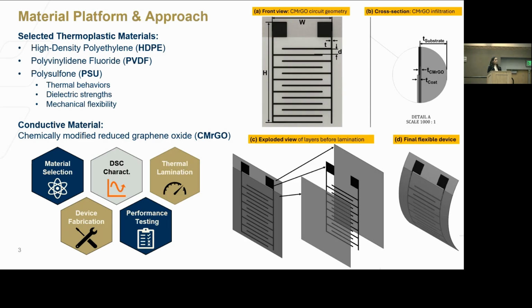Now, how we're achieving this is that we're basically thermally laminating the bottom three material layers you're seeing at the bottom. And because our thermoplastic materials are being softened with elevated temperatures and high pressure, they are interdiffusing into each other and their chains are entangling and cross-linking. On their way, they're also infiltrating whatever CMRGO particles we have in the middle so that we can get this nice flexible composite device. I also want to highlight the selected materials that we have here. We have high-density polyethylene, HDPE, polyvinylidene fluoride, PVDF, and finally polysulfone, PSU.